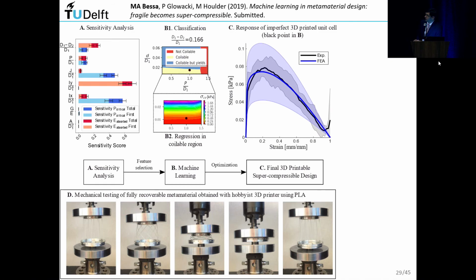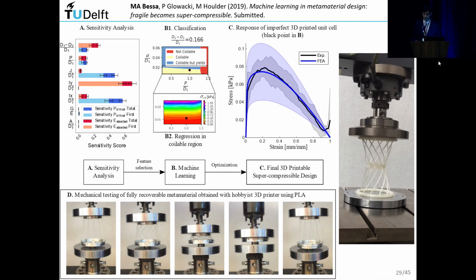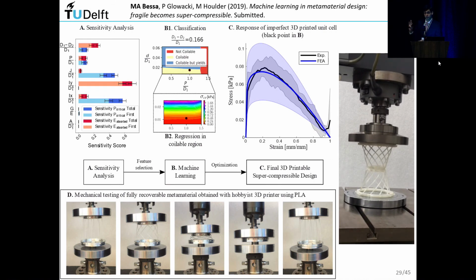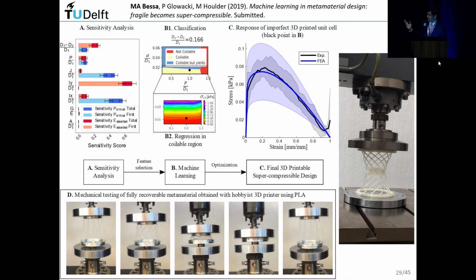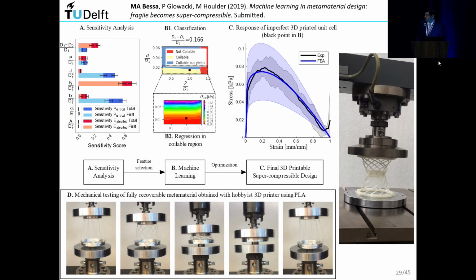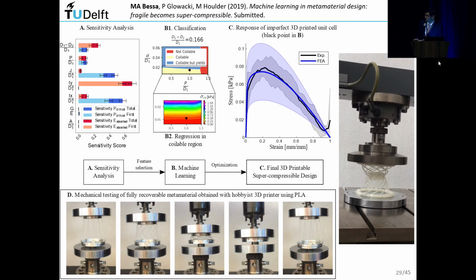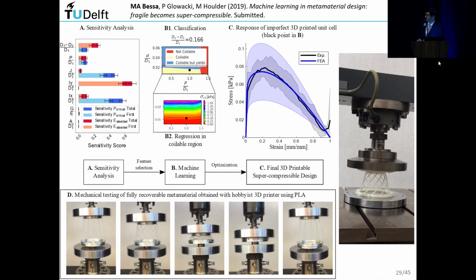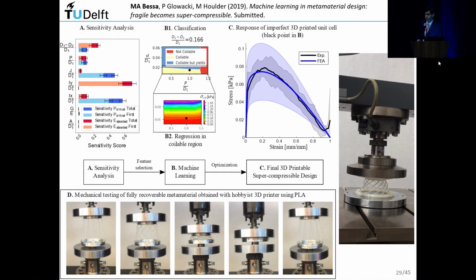And the black line is the experimental value with the standard deviation over there. And the blue line is the finite element prediction for that point and the standard deviation, taking into account the material properties, which were really wide because of the 3D printing process. You can actually have some fun and invert this unit cell, put two of them together, and achieve supercompressibility by rotating the middle ring over there and keeping the tops fixed.